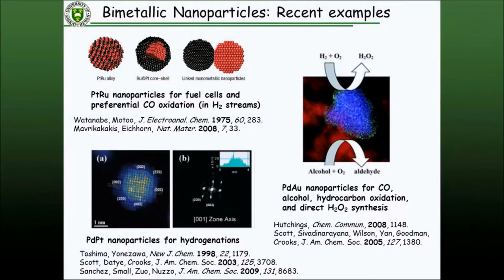Bimetallics have been all over the place in the last little while. In particular, Eichhorn's group has been doing a lot of work with platinum-ruthenium nanoparticles for fuel cells, for preferential carbon monoxide oxidation in the presence of hydrogen, trying to remove carbon monoxide impurities in hydrogen gas. Palladium-platinum nanoparticles for hydrogenations have been looked at by a number of groups. And the palladium-gold system in particular has been looked at by a lot of groups, in particular Graham Hutchings' group. All kinds of different reactions, and particularly the ones that have really attracted attention are hydrocarbon oxidations, alcohol oxidation, and now direct hydrogen peroxide synthesis from hydrogen and oxygen gas.